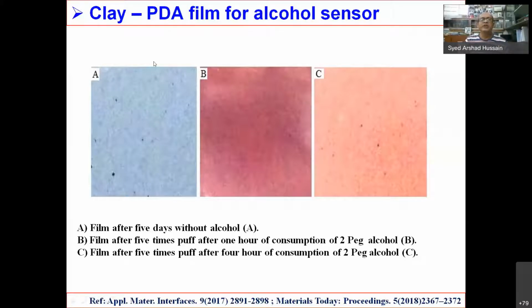Then what we did, we kept the film in front of a person who consumed alcohol, and he used to give a puff on the film, and you can see the color changes just based on the breathing. You can see the film after 5 puffs, after 1 hour of consumption of 2 pegs of alcohol, the color change. So the interesting thing is, it's something like litmus paper. Just observing color change, you can have an idea that at least, yes, the person is drunk.